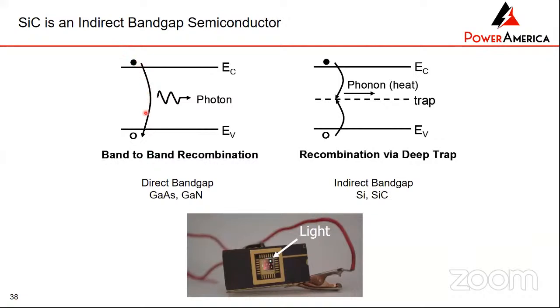And when you have a conduction to valence band transition, obviously, if it's radiative, you're going to generate light. In the case of silicon carbide, it's an indirect bandgap semiconductor. So you have to have both conservation of energy and conservation of momentum in order to produce light. So this is a silicon carbide device that I had made and put in a package. And you can see when you bias the device, it produces a little bluish, blue-purple light.